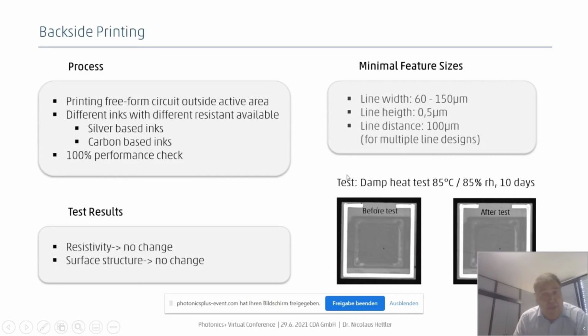So, of course, we did also here ongoing reliability checks. So we had a test, the typical 85-85 test, means 85 degrees Celsius and 85% humidity for 10 days in the climate chamber. And we measured resistivity before and after, there's no change. We measured the surface structure before and after, and we found no change. In general, if you compare the images, there's no change at all, and this is also the result from us.